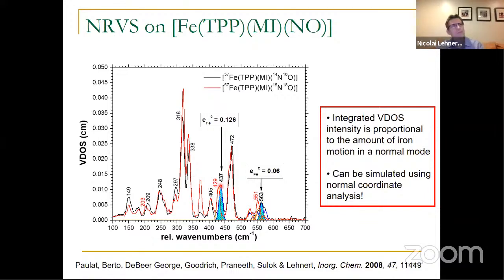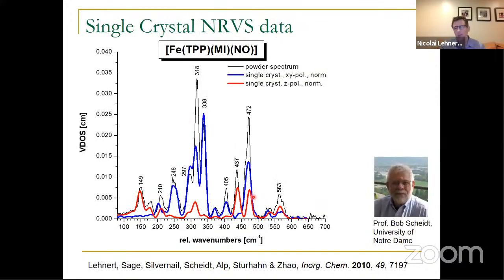But we still don't know how to assign these vibrations, right? We can identify these 2. One is the stretching mode, one is the bending mode, but we still don't know which one is which. But now we can do a further trick, and that is we do an experiment with single crystals. We did that in collaboration with Bob Scheidt's group at the University of Notre Dame, right? Where you make a single crystal of your complex, and then you orient the single crystal in the beam, and the beam is actually polarized.